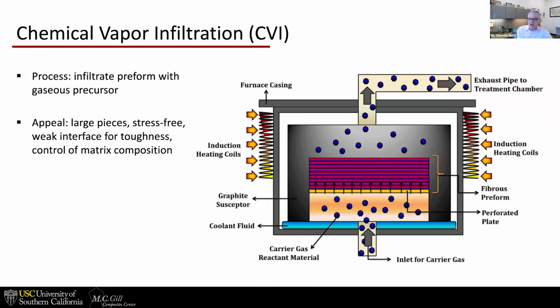A second process route is CVI, chemical vapor infiltration. The appeal is you can make large pieces and have very good control of the matrix composition, unlike reactive melt infiltration. This is basically chemical vapor deposition, but it's chemical vapor infiltration into a fiber preform. The challenge is, well, it's costly, it's very slow, and there's closed porosity. Porosity levels, as I understand it, between 5 and 10% are common, and cycle times are days, not hours, like 5 days, 10 days.